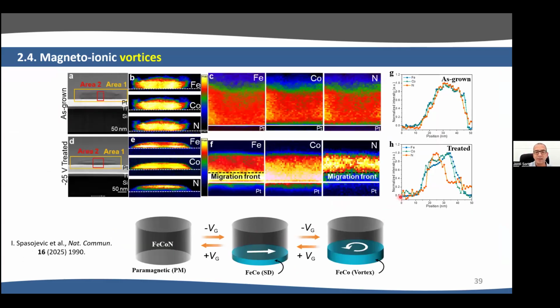Okay, here, interestingly, we could again see this planar migration front. This is the starting material, grown again homogeneous, and after gating, we could see accumulation of iron and cobalt at the bottom of the film and nitrogen at the top of the film.